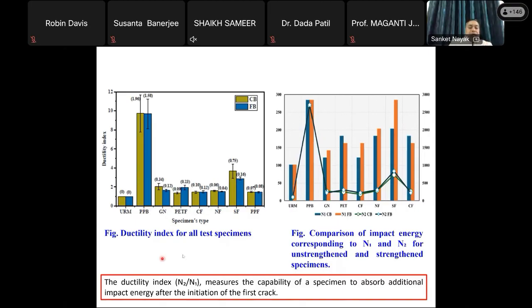Another aspect we have calculated is the ductility index. You know ductility is the property to achieve deformations without failure, to accommodate extra deformation without failure. The ductility index is the ratio of N2 upon N1. N1 is the blow where the first crack occurs, and N2 is where the failure occurs. So it measures the capability of a specimen to absorb additional impact energy after the initiation of the first crack. It has been plotted, and you can see for the PP band case, it is the best one.